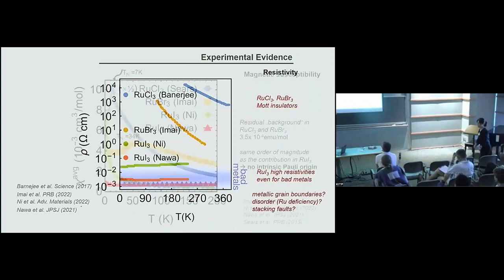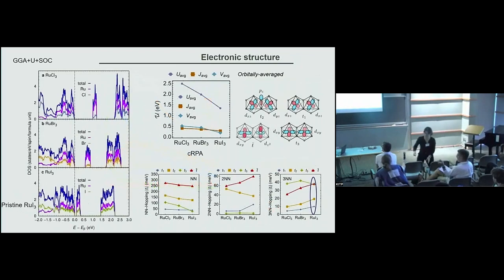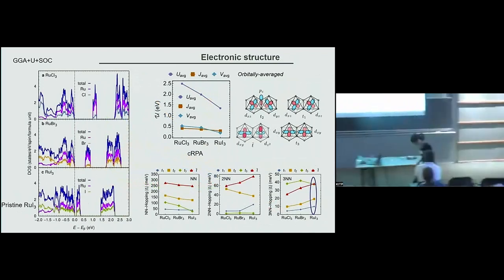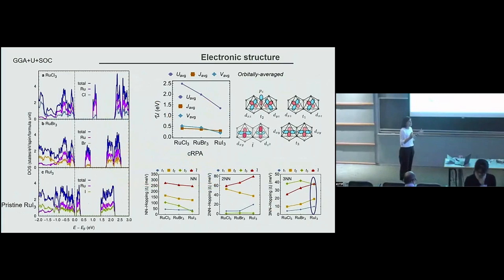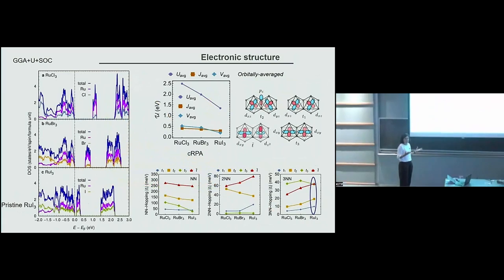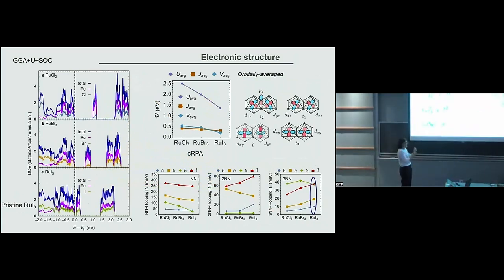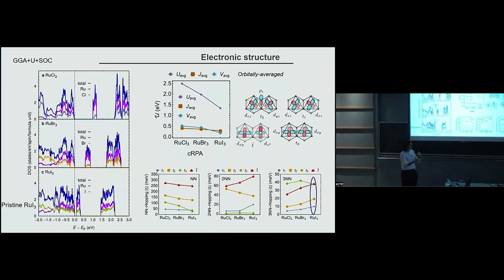So that's why you see the protocol, because this is an important point. The protocol that we follow in order to say something about the pristine ruthenium trichloride, because the way that you model Mott insulators in DFT is by doing DFT plus U or whatever. Depending on the U, I can take a large U and I will always open a gap. So we follow the protocol that we calculate these interactions by doing CRPA.